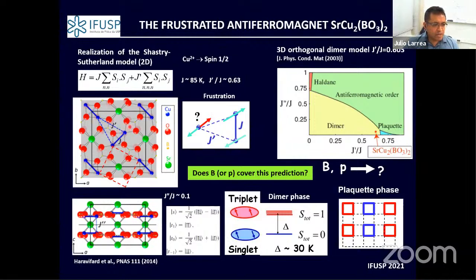Important things about the coupling inside the planes: the system shows an interesting coupling between spins, with the intradimer J versus the interdimer coupling J prime for next-nearest neighbors, whose ratio is not negligible. However, the coupling between layers along the C direction is very negligible, so the system can be considered uniquely as a bidimensional system.